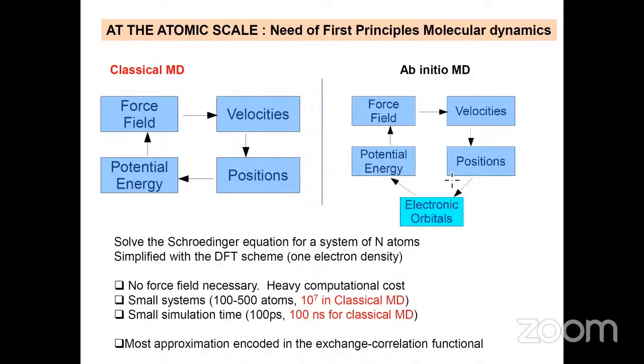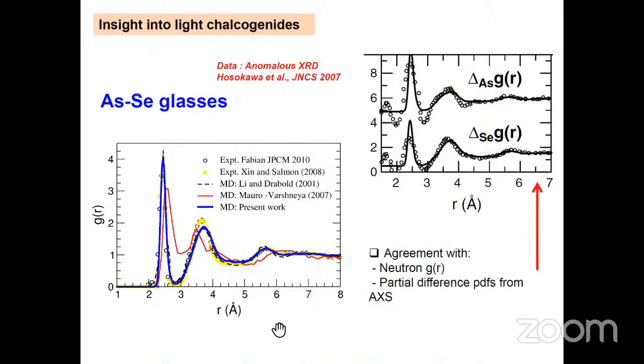So in principle, in ab initio MD, you don't need force fields. It's of course a heavy computational cost because it's self-consistent, and basically it reduces the number of atoms of your system. So you're dealing basically with 100 to 500 atoms, whereas it's about 10 to the 7 in classical MD, and the simulation time is reduced to 100 picoseconds. But it provides very, very nice agreement with experiments.